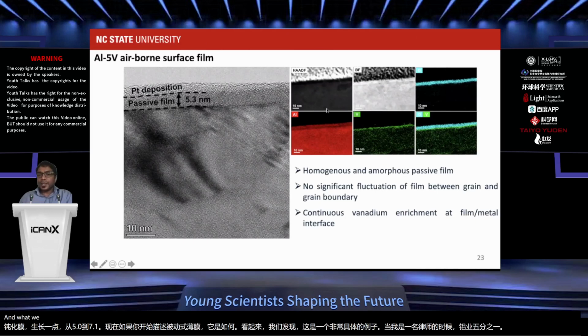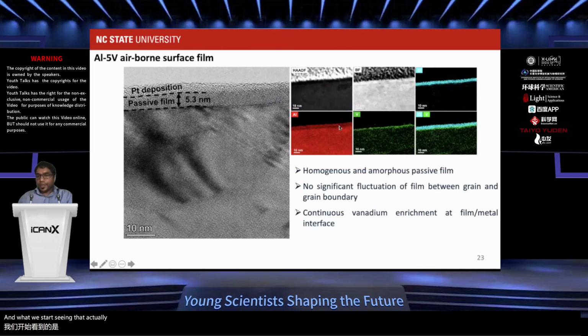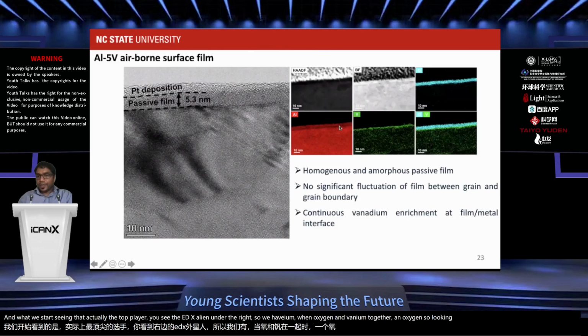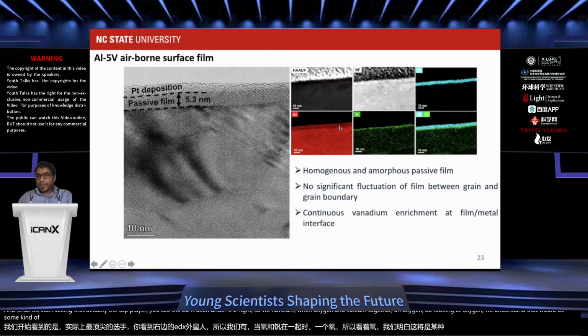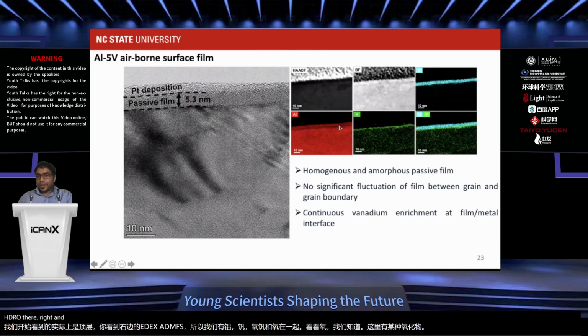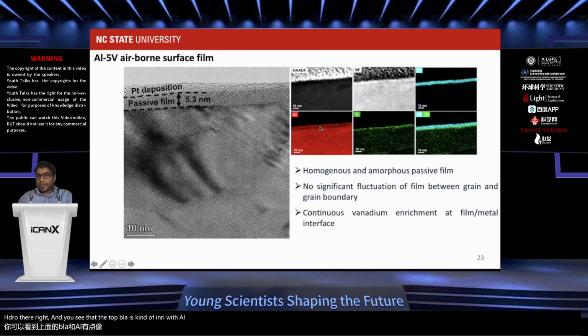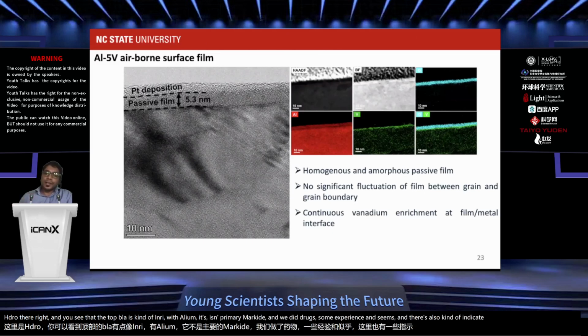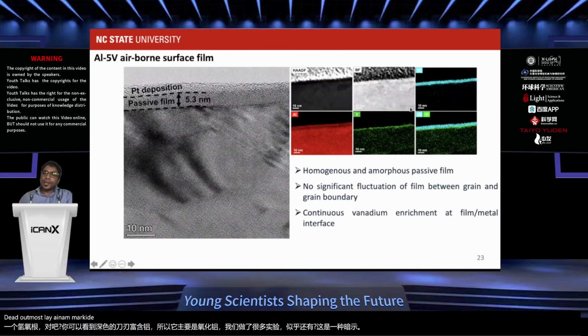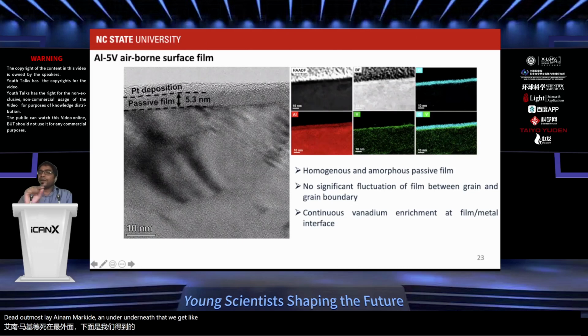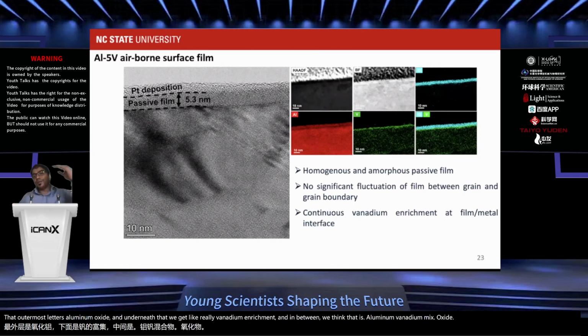What we start seeing is that actually the top layer, you see the EDX area maps on the right. So we have aluminum, vanadium, oxygen, and vanadium together, and oxygen. So looking at oxygen, we understand that there would be some kind of oxide or hydroxide there, right? And you see that the top layer is kind of enriched with aluminum. So it's primarily aluminum oxide. And we did lots of XPS and SIMS, and they also indicate that the outermost layer is aluminum oxide. And underneath that, we get really vanadium enrichment. And in between, we think there is aluminum vanadium mixed oxide. So you have aluminum oxide, aluminum vanadium mixed oxide, and vanadium oxide.